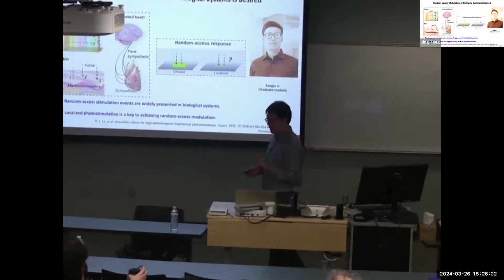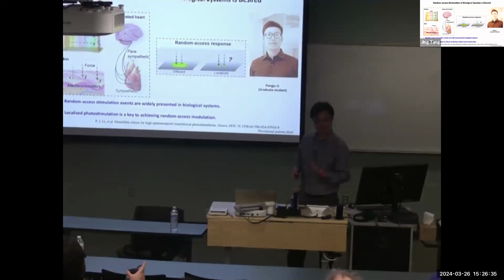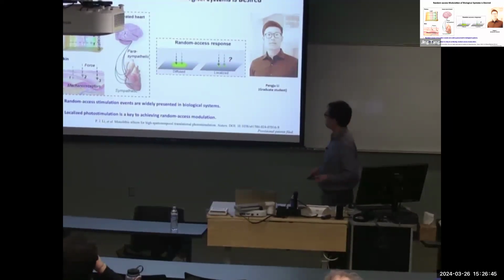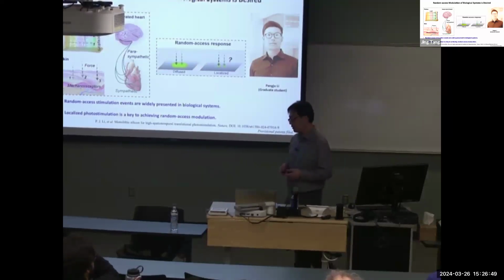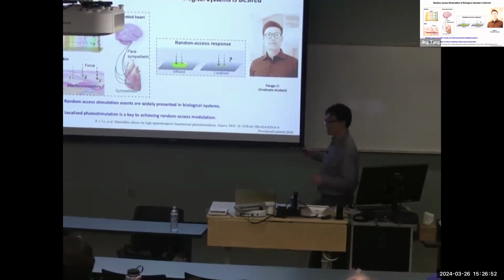For many years, we have been thinking, how can we improve the precision of stimulation, right? It's not just to one spot, but to multiple locations so that you can actually target a certain conduction pathway. And the question is hard to address. Why? If you use just a monolithic silicon membrane, like a traditional solar cell, when you shine light, the photogenerated carriers can spread to a very large area. This is very good for a traditional solar cell because it is good for carrier collection. But it's very bad for photostimulation, because if it diffuses, you cannot differentiate the impact from those two light spot locations, because the carriers essentially got blurred.